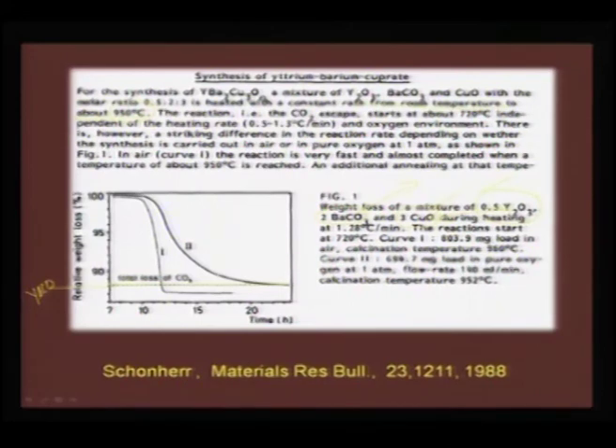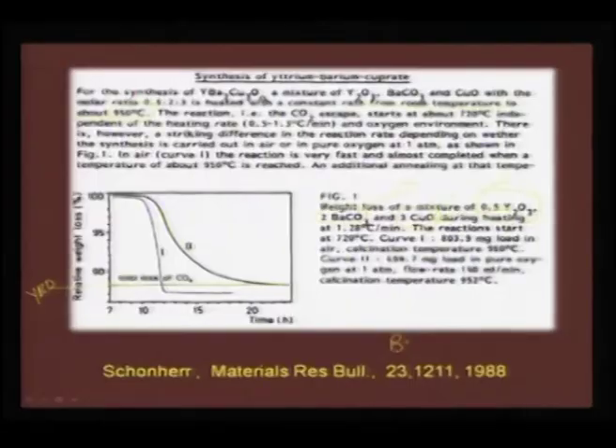So, many wet chemical routes have been brought in where barium carbonate can be avoided and reactive barium oxide can be used. One of the convenient ways this has been achieved is to take barium peroxide, and barium peroxide above 400 degrees C releases reactive barium oxide. As a result, at any temperature above 400, you will have a very reactive mixture of yttrium oxide, barium oxide and copper oxide. Therefore, the single phase compound can be made with ease.